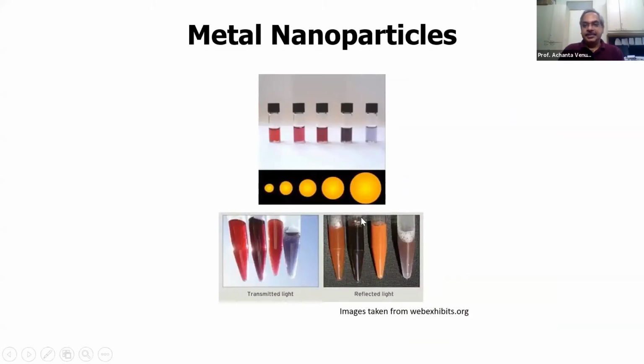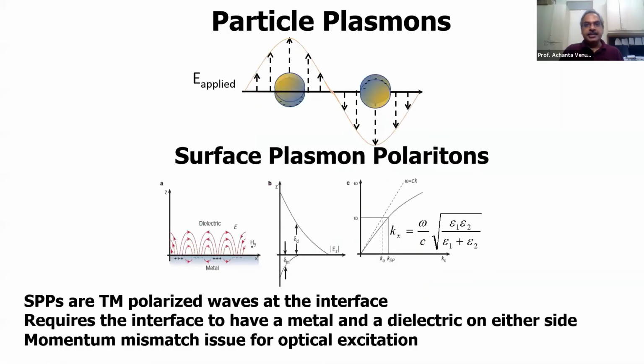Right. So for that, we need to understand why metal nanoparticles have different colors. For example, if you take gold nanoparticles of different sizes, these are all spherical particles. The only difference between them is that they are of increasing sizes. What you see, if they are suspended in water, is that they show different scattering colors. Both the transmitted and reflected colors will be different. For example, if you take the smallest size, its transmitted color is red, but the reflected is an orangish color. Right? So they have different scattering colors, both in reflection and transmission. So why does this happen?